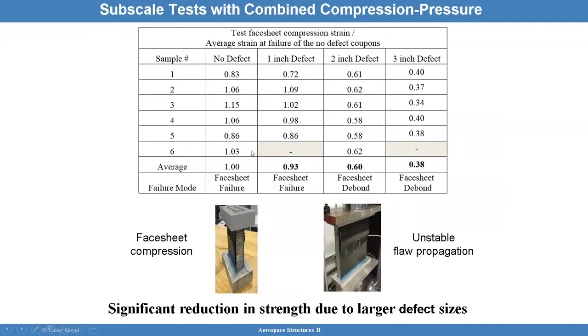Here are the results. Two of the failure modes for small defect size were face sheet failures. The other two were face sheet disbonds. There are six samples: no defect, one-inch, two-inch, and three-inch defects. A three-inch defect has a huge strength reduction compared to the no-defect case. The one-inch defect is not too bad. There's one outlier at 72% — that would be interesting to investigate. For the two-inch defect, you're looking at about two-thirds of the full capability.